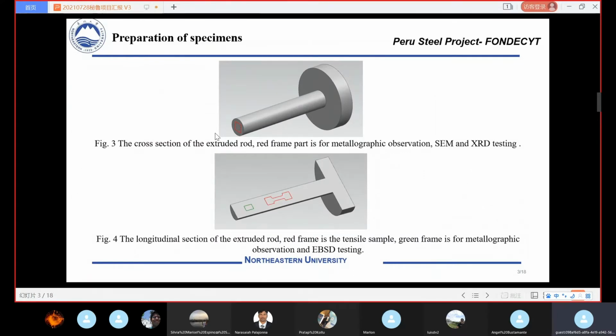After we get the extruded rods, we prepare the specimens for microstructural observation, phase identification, and tensile tests. Later we will talk about the tensile test, which is used to measure the mechanical properties. We took two kinds of samples. One is the cross section of the extruded rods. This red frame part is for the metallographic observation, SEM and XRD testing. The metallographic observation and SEM are to analyze the microstructure, and XRD is used to identify the phase constitution.